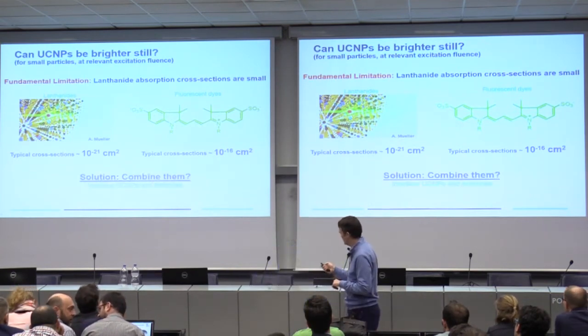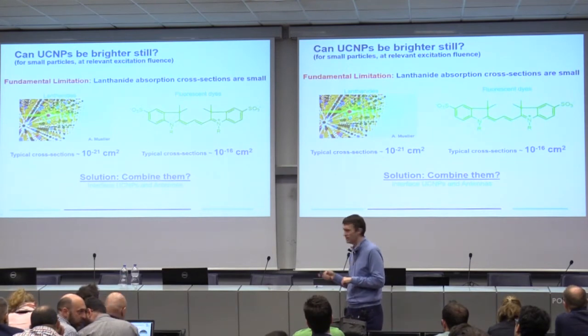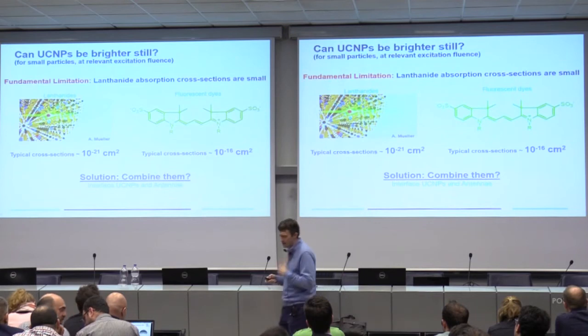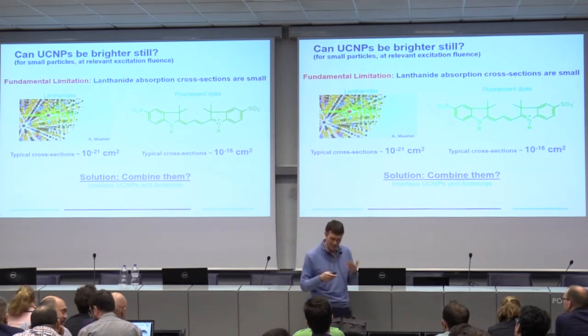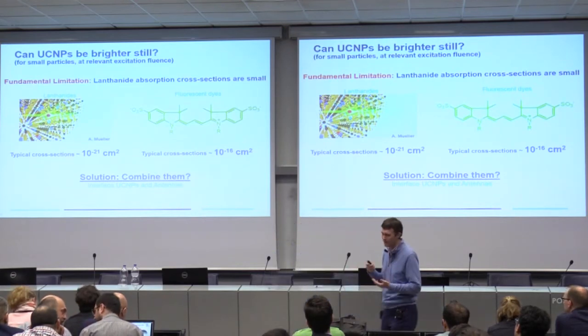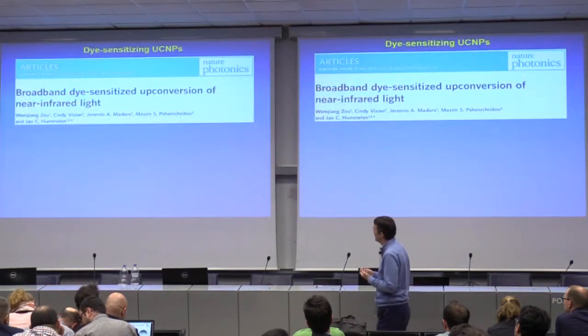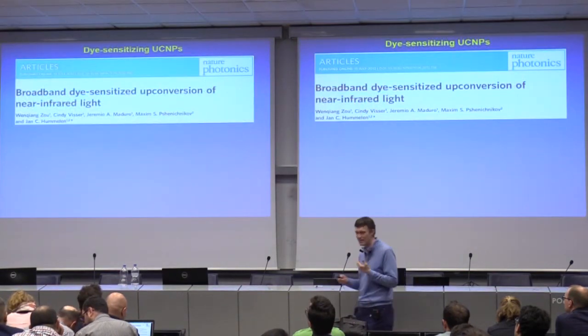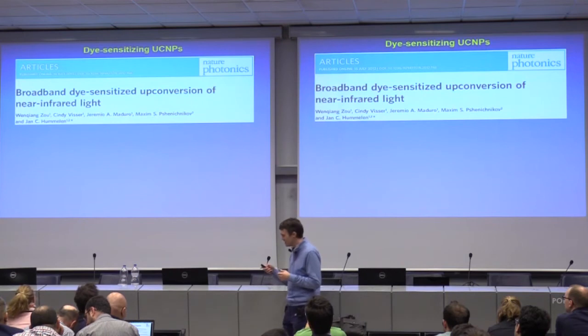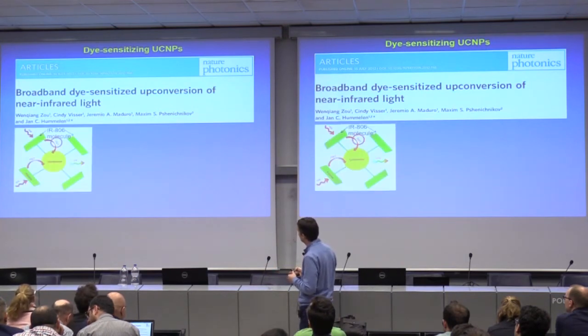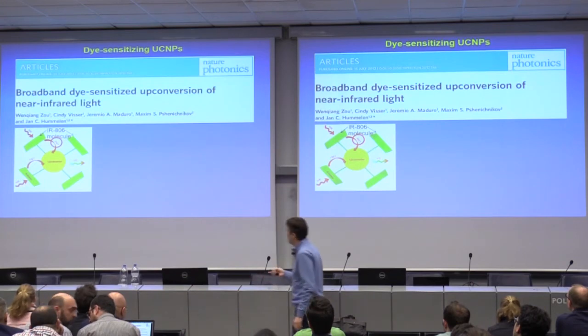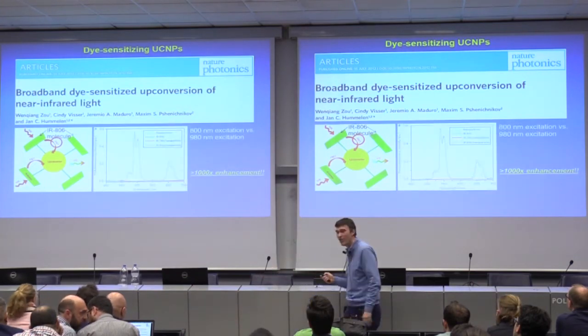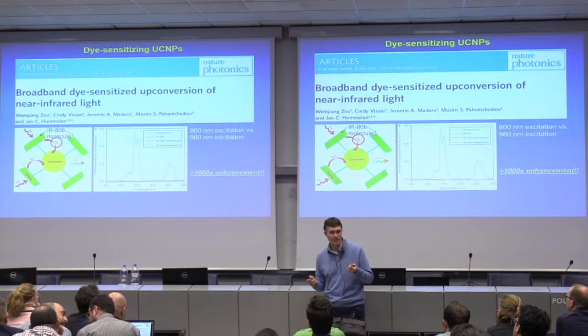The solution is to take a dye and use it as an antenna to funnel energy into your upconverter. This idea was bouncing around the upconverter community for a while, and while we were all talking about it, Jan Hummelen's group just did it. They stuck dyes on an upconverting nanoparticle. They published this in Nature Photonics in 2012 and showed that, in fact, they could get 1,000 times brighter particles just by putting dye molecules on it.